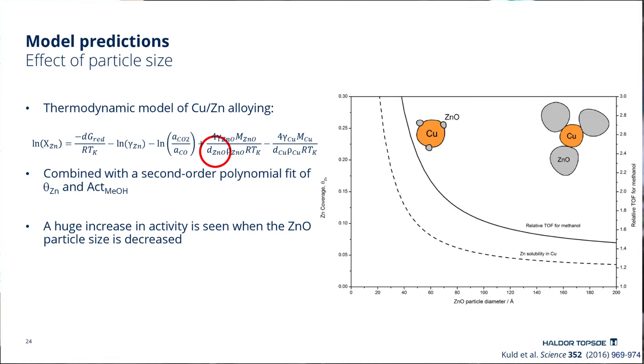On the left y-axis, you have the zinc coverage on your copper particles. And on the right y-axis, you have the relative turnover frequency of methanol. And here on your x-axis, you have the zinc oxide particle size. So this has nothing to do with the copper, which I told you is the active phase initially, or at least it has only a secondary relation to copper, you can say. But what you can see here, and what is really exciting, is that if you decrease the particle size of your zinc oxide particles in the catalyst system, you really seem to boost your methanol activity.